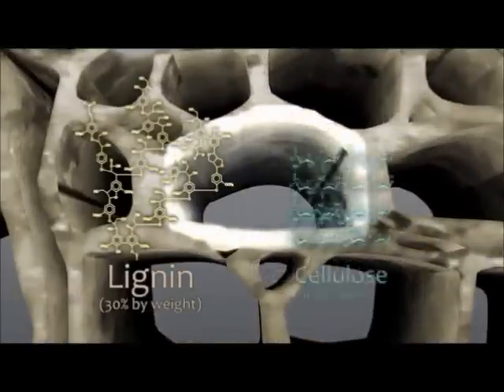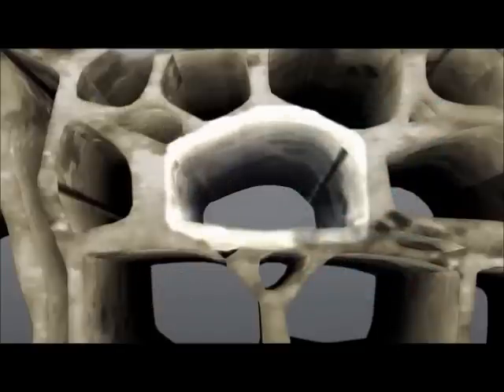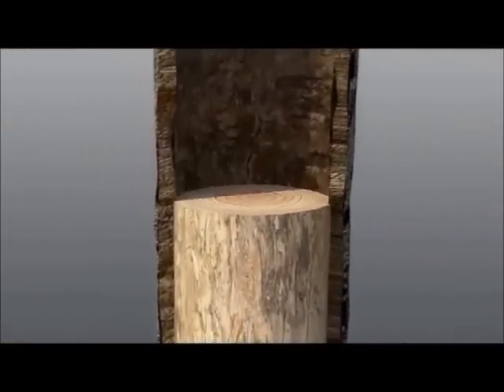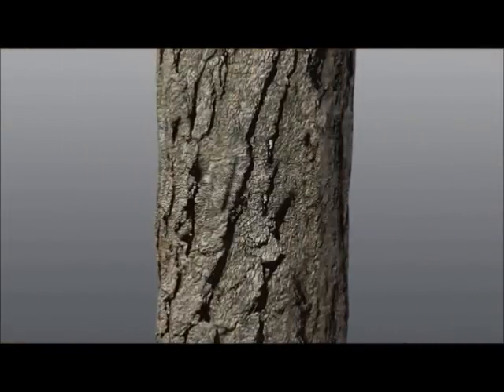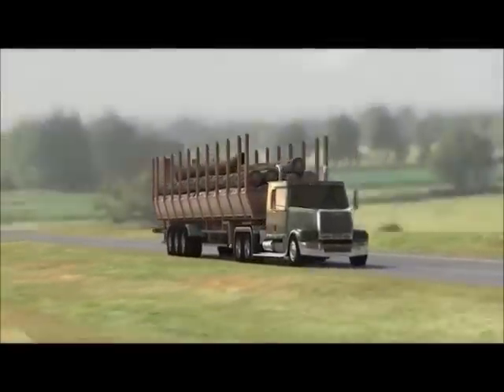The majority of lignin removed from biomass is burnt on site for its energy content. Lignin is an attractive precursor for the production of CNFs, not only because of its abundance and low value, but also because it has a highly aromatic molecular structure that results in a large carbon mass yield after carbonization when compared to other natural polymers.